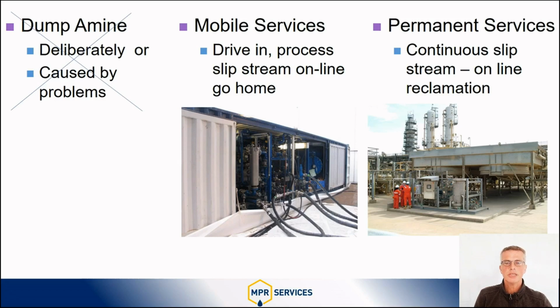It's much better to reclaim the amine on a regular basis, or even better, continuously, like a kidney. That can be done by techniques like ion exchange, electrodialysis, or vacuum distillation. In amine solutions, MPR Services uses a special ion exchange process, since it can clean to very low levels of heat stable salts and amino acids. Reclaiming is normally done online on a slipstream, while the amine system is operating.